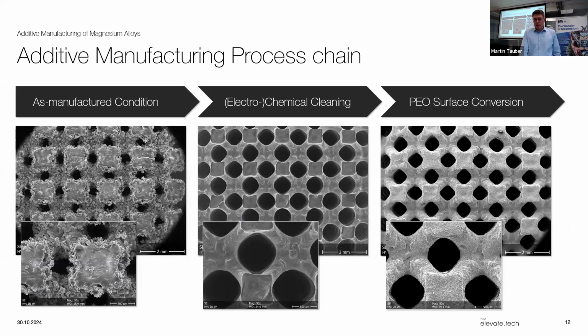The last step that we do in-house, which is a big field at Meotec, is the PEO surface conversion. As you know, magnesium is a quite reactive alloy and it's degrading or corroding quite fast. And this corrosion, we want to have this degrading in the human body because that's the idea of the material, but we don't want to have it too fast. So this PEO surface conversion makes it possible for us to slow down the degradation, to have a degradation protection of the material. And this is also an electrochemical process. And as with the electrochemical cleaning, the process is capable of reaching all regions of the part and building up a surface conversion layer inside and out.